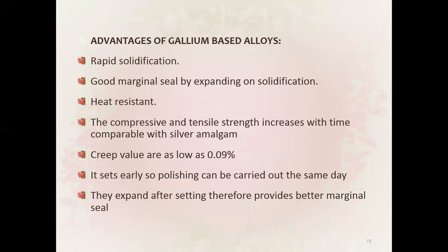The compressive and tensile strength increase with time, comparable with silver amalgam. Creep values are as low as 0.09%. It sets early so polishing can be carried out on the same day. They expand after setting, therefore providing a better marginal seal.